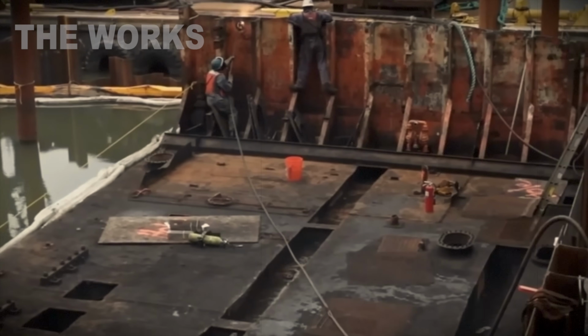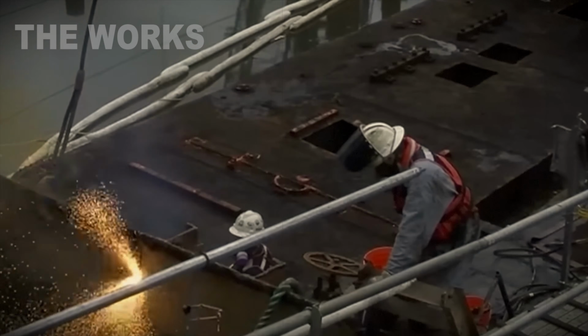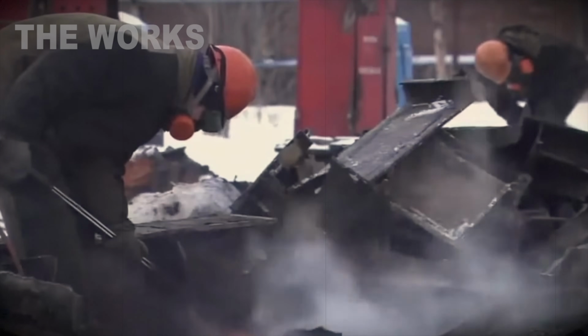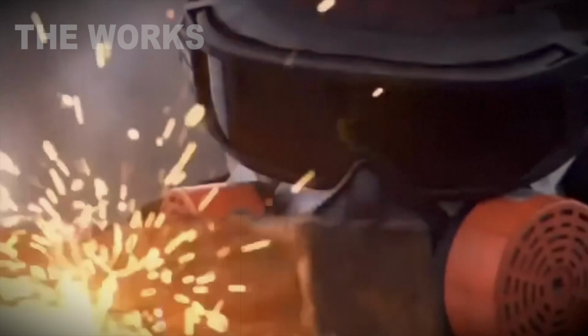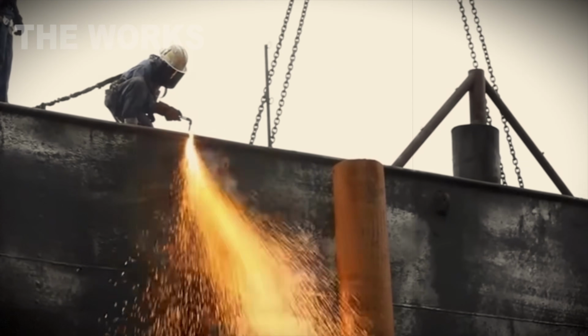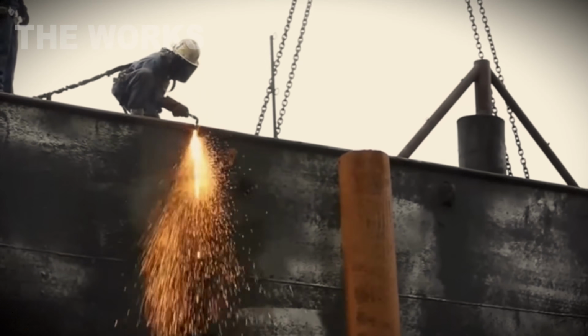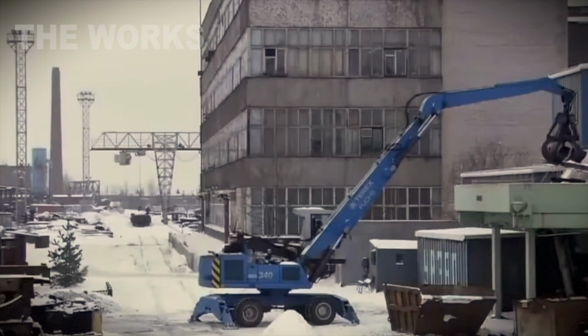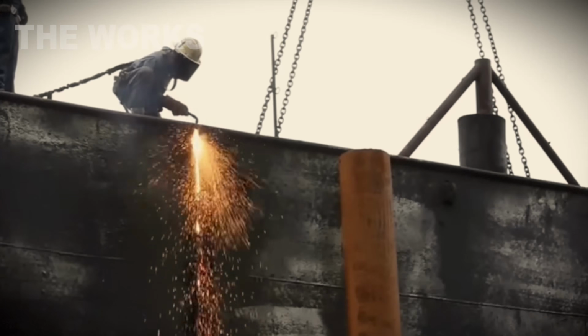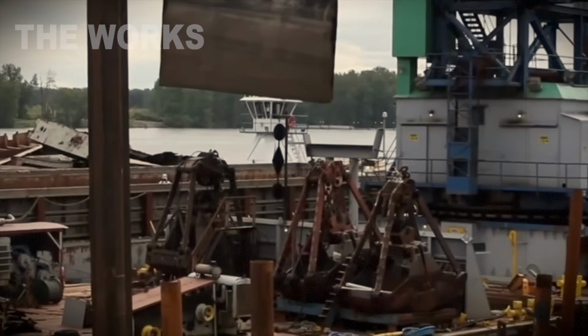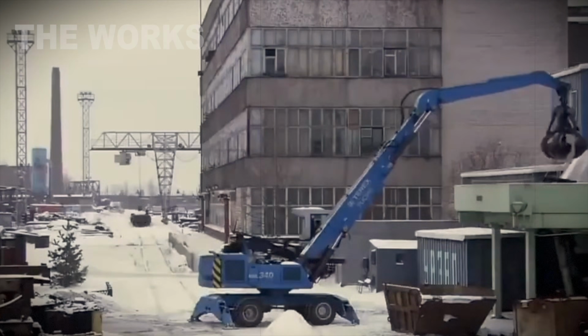Cutting the hull. After decontamination, the submarine is ready for final dismantling. The submarine's hull isn't ordinary metal, it's an alloy built for war. It withstands water pressure at depths of 1,000 to 1,300 feet. That's 30 to 40 atmospheres. Hull thickness, 3 to 4 inches. A K29 grade steel. Tensile strength, 100,000 pounds per square inch.